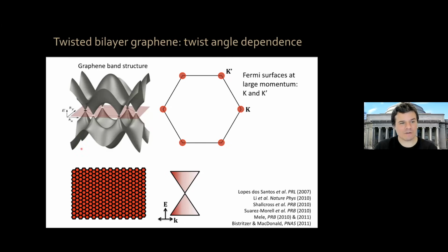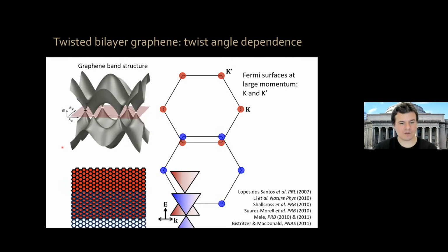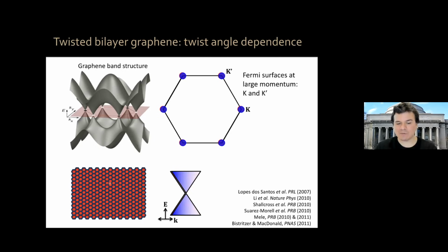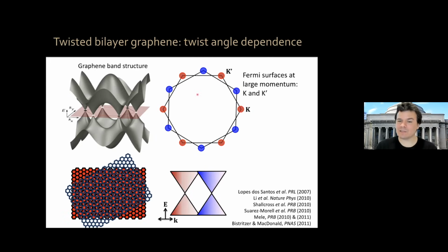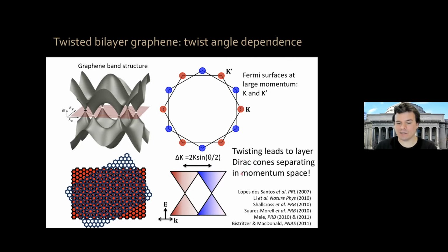So now let's put graphene on top of graphene, okay? If we perfectly align them in real space, the reciprocal spaces are also aligned. If we rotate in real space, the reciprocal spaces also rotate. And that means that the Dirac cones of layer 1 and layer 2 become separated in momentum space, okay? That separation is proportional to the sine of the rotation angle divided by 2, okay?